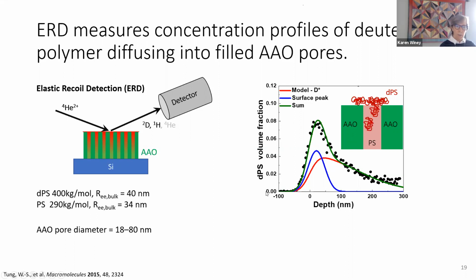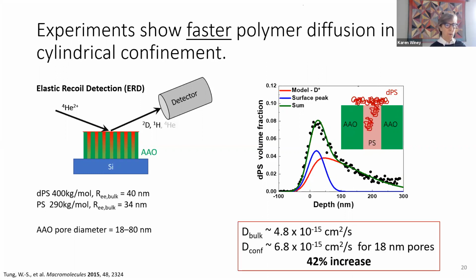Now this is a concentration profile for the deuterium, from the free surface into the depth of the pore. This green curve is all the deuterated polymer. You'll first see that there's a surface peak. There's a little bit of polystyrene that just stays on the surface because it's hard to get from on top of the oxide into the pore. But the stuff that gets into the pore goes like this. That's the red curve, and then you sum the red and blue curves to get the green. Without going into a whole lot of experimental results, I'll just share one.